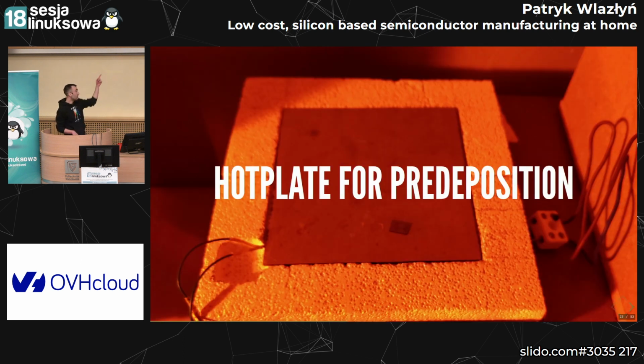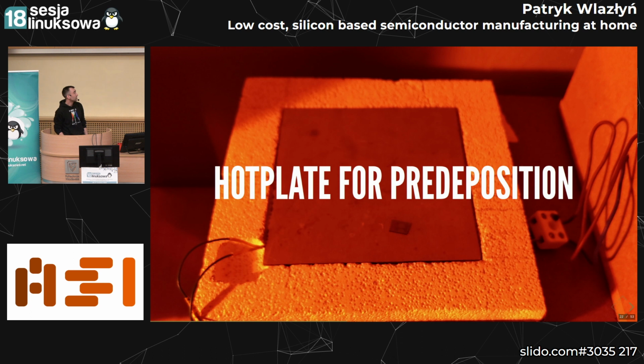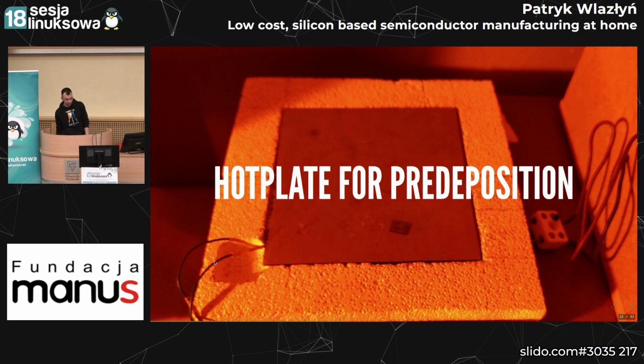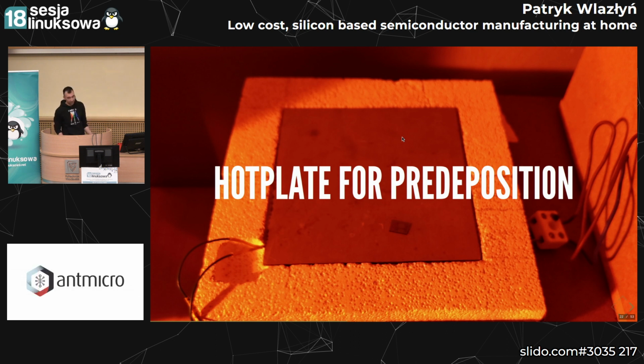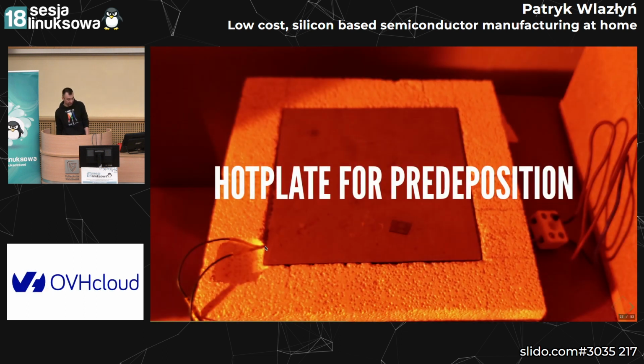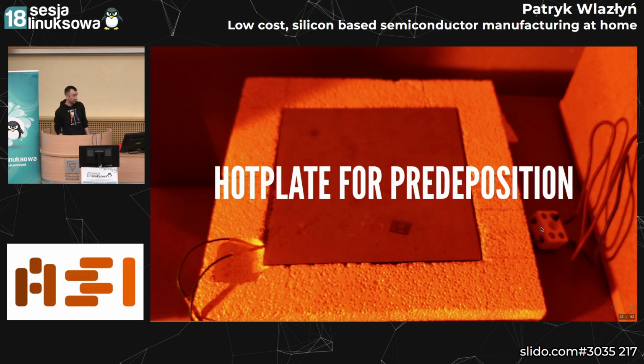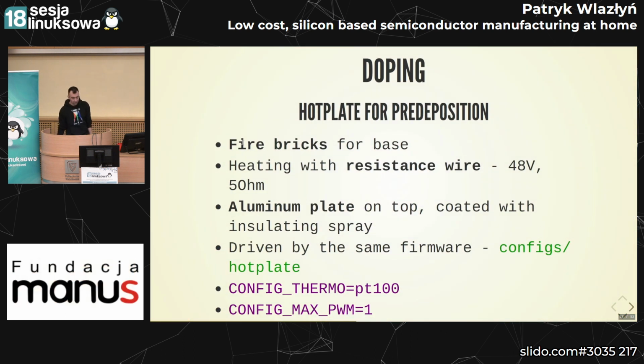And this is the hot plate that we've built. It's similarly built like a furnace. It has fire bricks for the base, an aluminum plate on the top, and beneath is a resistance wire. So basically the setup that we have for a furnace. There is a PT100 temperature sensor here that is constantly reading the temperature, so the Raspberry Pi can enable and disable heating to reach the target temperature. Again, we build this with fire bricks, and we have a resistance wire and aluminum plate on the top.